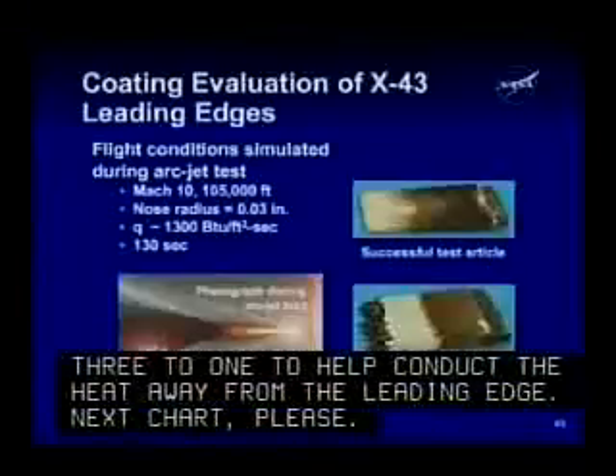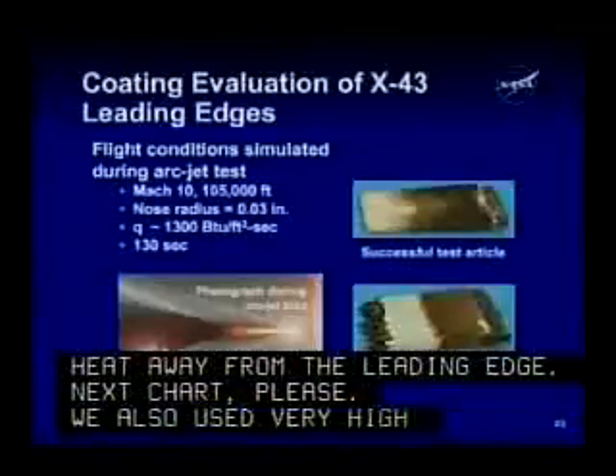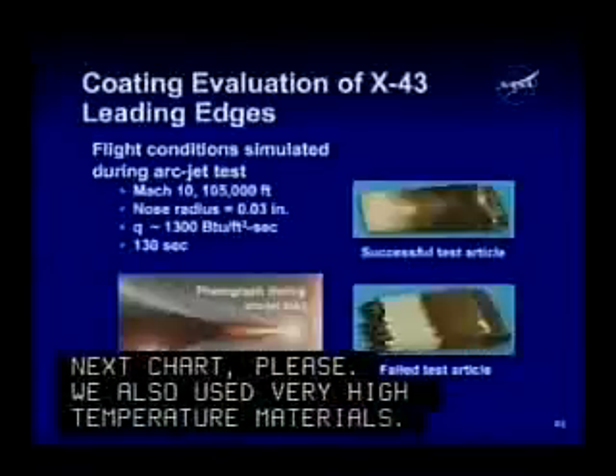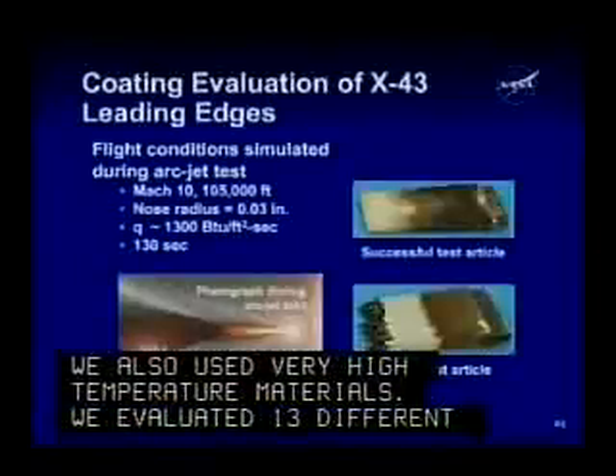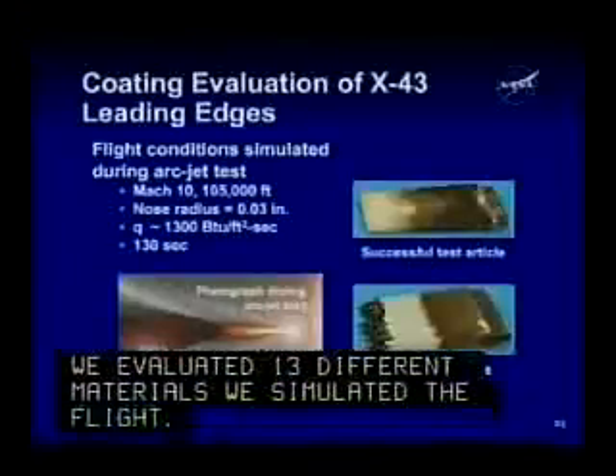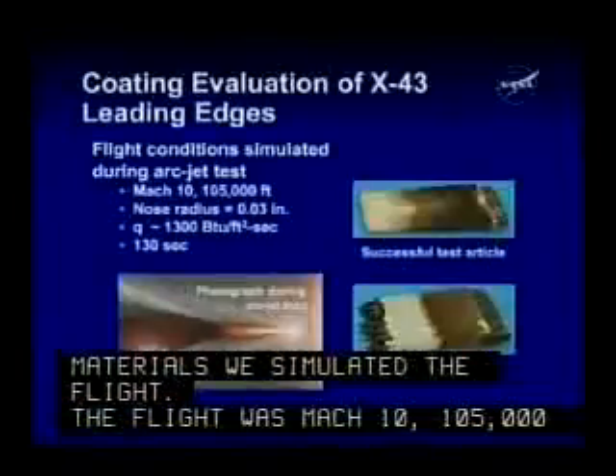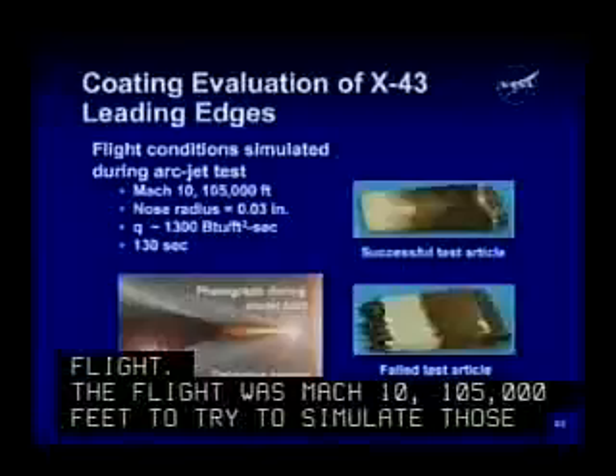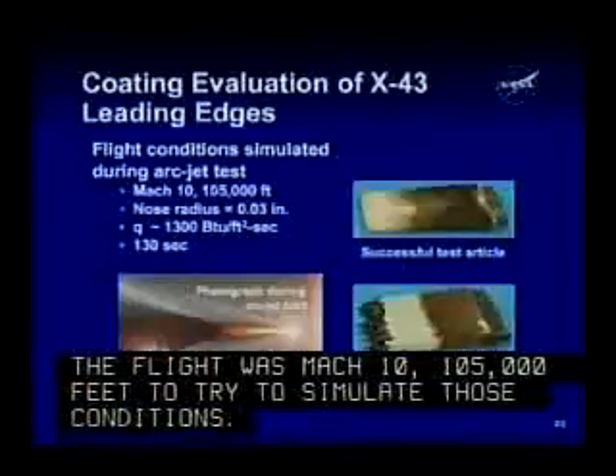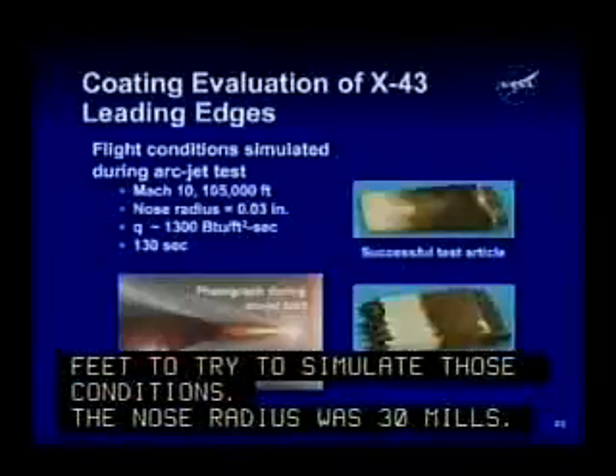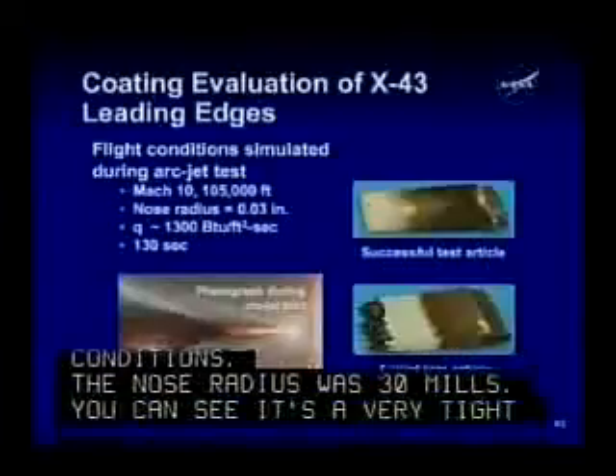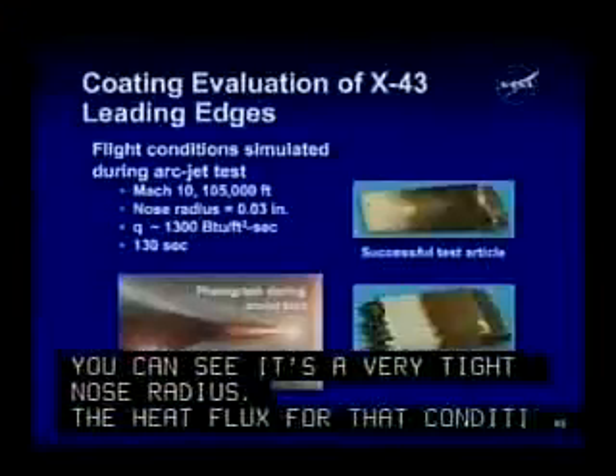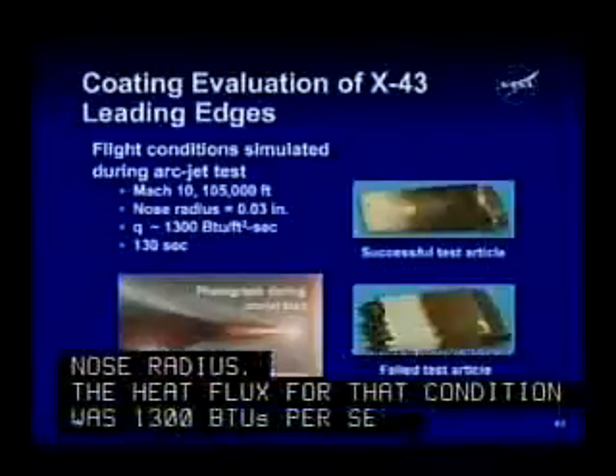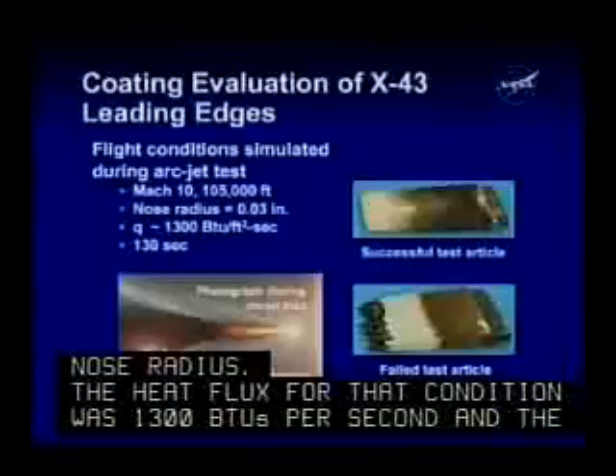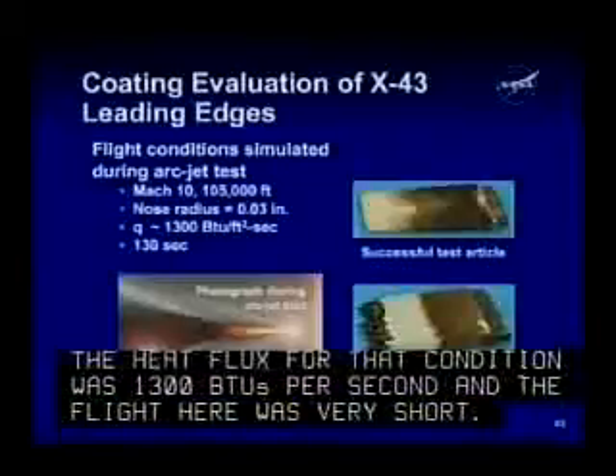We also used very high temperature materials. We evaluated 13 different materials. We simulated the flight in arc jet conditions. The flight was Mach 10, 105,000 feet, and we tried to simulate those conditions. The nose radius was 30 mils, so you can see it's a very tight nose radius. The heat flux for that condition was 1,300 BTU per foot squared second. And the flight here was very short, 130 seconds.